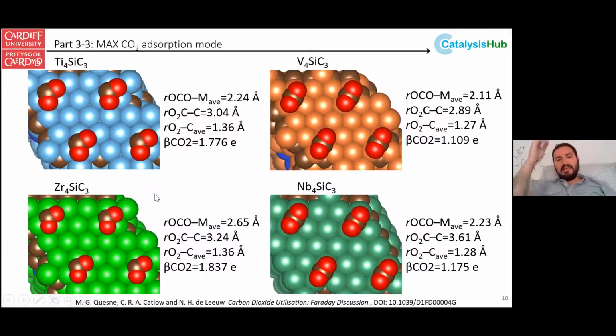So we find that in fact we get more than 1 electron reduction in the CO2 on the titanium and zirconium carbons. So it's not just the electron that we put into the antibonding orbital. We also get some rehybridization and formation of some sigma bonds. So we get about 1.8 of an electron in zirconium, and we have about 1.7 in titanium silicon carbide. We see about 1 electron reduction in the vanadium and niobium case.